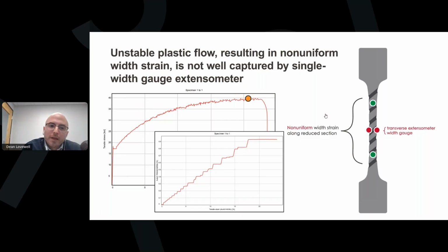Now, since we're missing the influence of that additional width strain on our R value calculation, that means that our calculated R value is going to drop throughout that plateaued period, as the formula assumes that the additional strain must be occurring from somewhere else. It doesn't see it in the width strain, it doesn't see it in the axial strain, and so it assumes it's coming from the thickness. This leads to large swings up and down in our R value calculation.